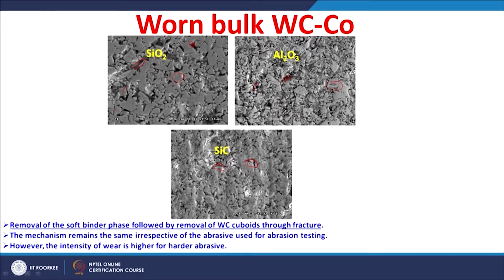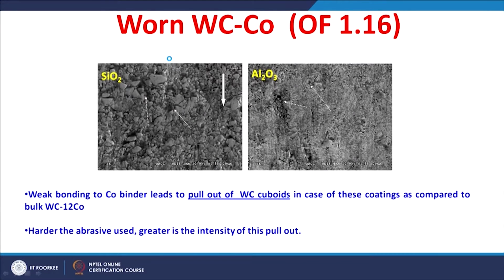This mechanism does not change with abrasive used. However, the intensity of the wear is higher when we use the silicon carbide, which is a harder abrasive, as compared to the abrasive wear obtained with the softer abrasive silicon oxide. Now, let us see the worn surfaces of the tungsten carbide cobalt coating. These are the worn surfaces of the coating obtained with a 1.16 oxygen to fuel ratio.